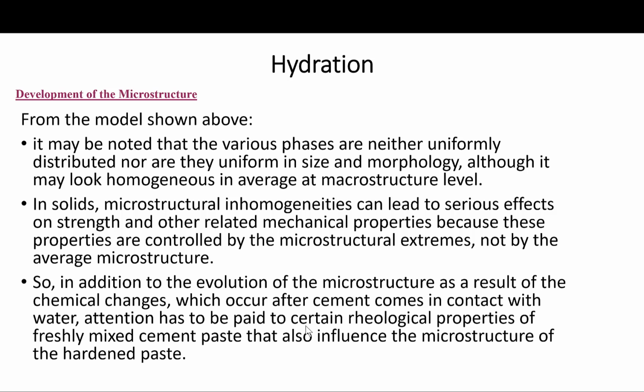With a highly flocculated cement paste system, not only the size and shape of the pores, but also the crystalline products of the hydration would be different when compared to a well-dispersed system.